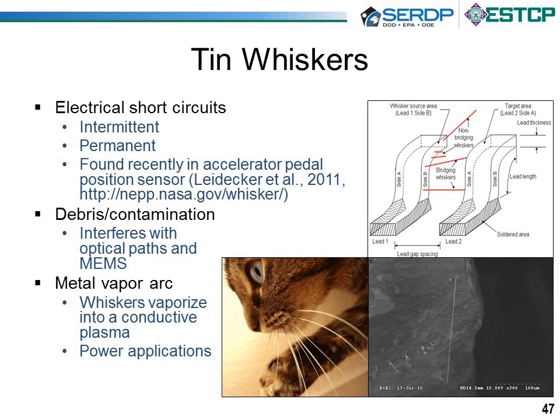And so as we spend some time with tin whiskers, we take a look at some of the electrical shorting concerns. They can develop permanent or intermittent shorts depending upon the amount of current available. If you've got enough current, it'll result in an intermittent connection because the whisker will fuse. If you don't have so much current, it'll be permanent. It also showed up in a recent accelerator pedal position sensor. You can look that up on the NASA website. It didn't really cause high acceleration, but it did result in some pretty erratic behavior of the system, and so that's a good read. It has a lot of good stuff about investigating whiskers and trying to track them down.